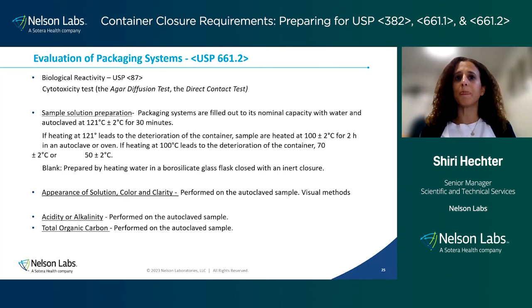However, the exposure time is critical because some systems will deteriorate at this temperature. And if a deterioration is observed, and it's usually observed by extreme changes in the way the solution looks, if it changes colors or turbidity, or any changes to the packaging itself during autoclaving, then it is allowed to use 100 degrees for a certain time. And if 100 degrees is also too high, then 70 degrees or 60 degrees or 50 degrees at the specified time.